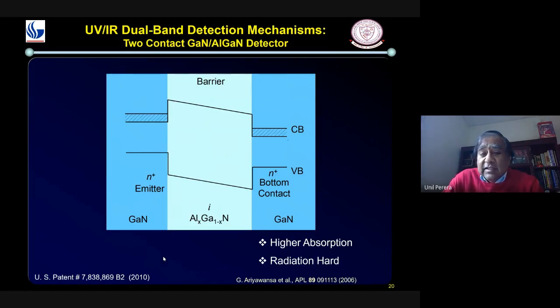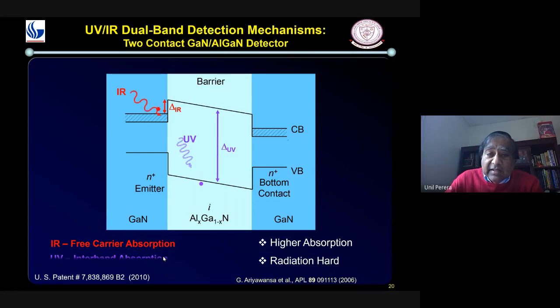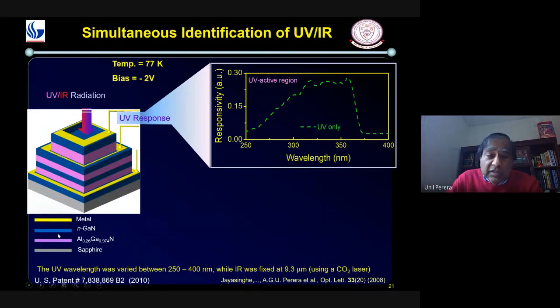So we have added this and extended that to a UVIR dual band detector, where we use both interband and intraband. Interband, this is intraband or inter-subband. So that is inside one band. This is what I was showing you just before, coming through just in one band. But the normal detectors earlier were going from one band to the other band. That is interband. So if you use gallium nitride, aluminum gallium nitride, you can detect both infrared and UV in the same device. So this is something we have developed for Air Force, and we have a patent and all that for this type of detectors too. So this is a structure for that.